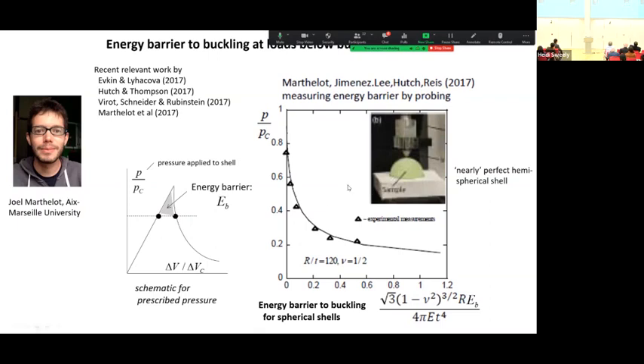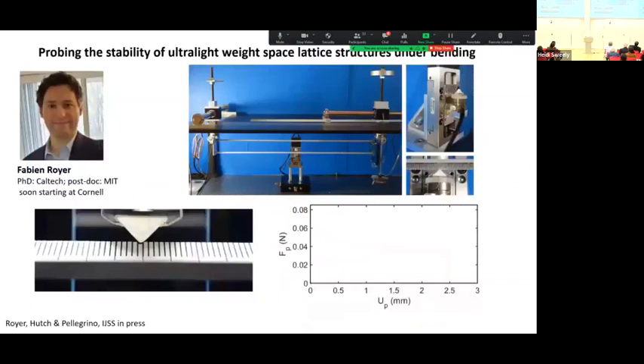And so we've done that, and Joel did the experiments where, once it's loaded in pressure, and this was prescribed pressure, he then probes it until it fails, and he measures the work he has to do to get it to buckle. That's actually an upper bound to the energy barrier, but it turns out for this configuration, that is essentially the energy barrier. And just remarkably good agreement between theory and experiment.